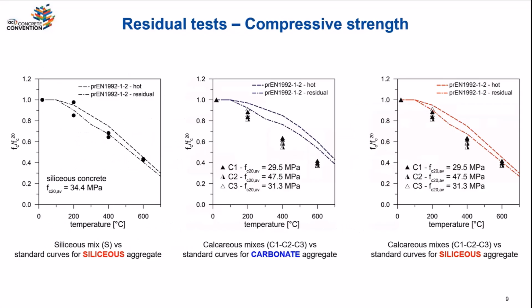These results show the measurements for the residual test. So these are the tests when we heat it up to a certain temperature Tmax, and then we cool down all the way to 20 degrees C, and we tested the residual value. So we had different mixes, and I'm not going to go into the details, but what's very important here is that the residual strength is below the curve, the provisions for the hot value, for the elevated temperature strength. Okay, so you see here for different mixes, we are always below this hot curve. It means that there is additional degradation of strength during the cooling back to ambient temperature.